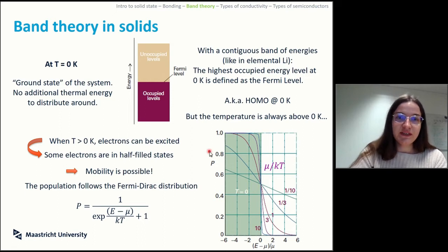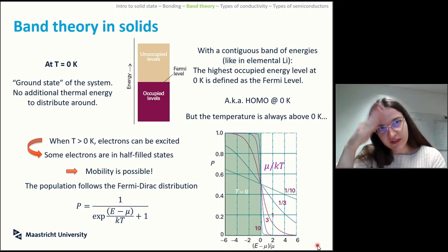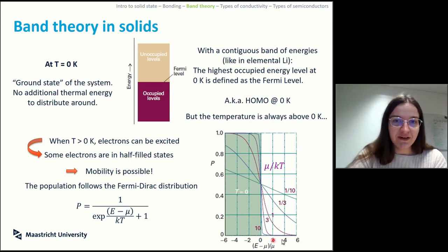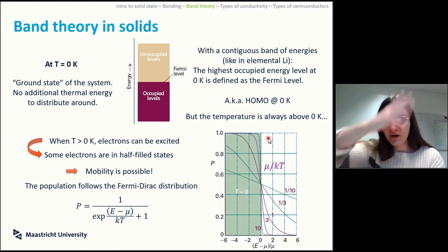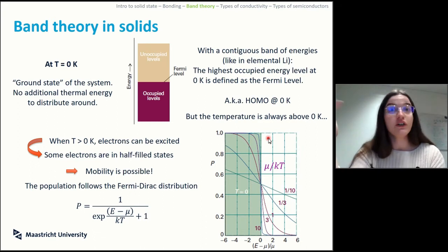The more you go, the more it resembles a Boltzmann type of distribution. So exponentially, with increased energy, you decay down. So the higher the temperature, the longer the tail. At relatively low temperature, the tail here is very tiny. The higher you increase the temperature, the more the tail shifts and gives you more and more energy states in which your electrons are free to go by thermal energy. Bam!